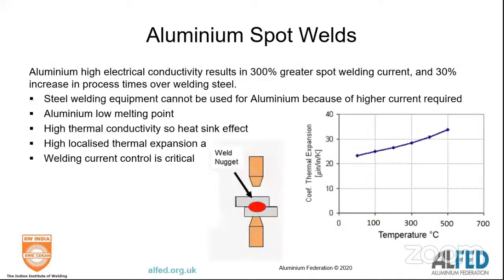Implications for spot welding. In essence, if you're going to spot weld aluminium, you need about 300% more welding current and about a 30% increase in process times. Typically, that means you can't use steel spot welding equipment for aluminium because of the higher currents. You've also got a heat sink effect: you've got a tiny weld with big thermal conduction. So current is very important, and you've got high thermal expansion surrounding your weld bead.